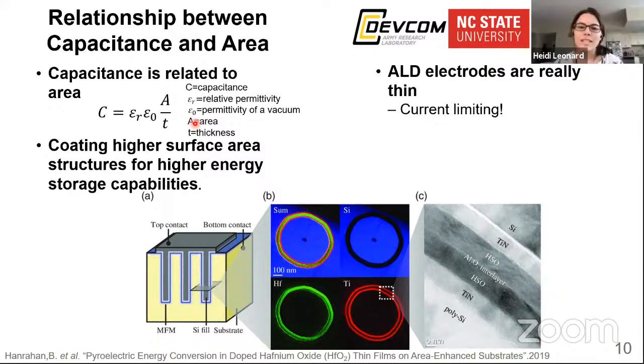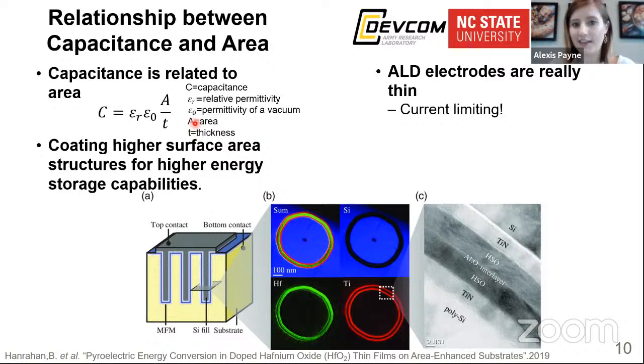Right. I guess along with that question, Brendan is asking, what's the ideal composition and how would you choose? So the ideal composition is determined by looking at how these thin films operate at their operating voltage. You just don't want to pick the film that can withstand the highest field or just look at one specific property. You always have to go back to how is this functioning at the actual operating voltage it would be used at, and what has the greatest efficiency and what has the greatest energy storage density. And we haven't done a complete study of all the doping concentrations and thicknesses yet, but from the ones we studied, we believe that the 8% aluminum doped hafnia at 50 nanometers is the best.